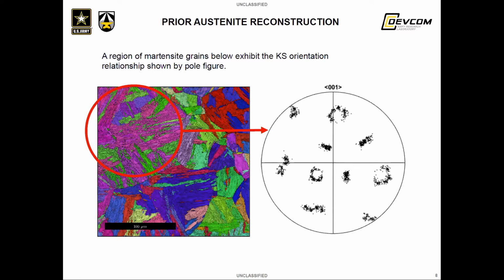Note that the martensite orientations are not perfectly aligned with the theoretically defined variants in the previous pole figure. There are many sources of deviation from the formation of perfect variants, so the choice of orientation relationship is often made to minimize that error.